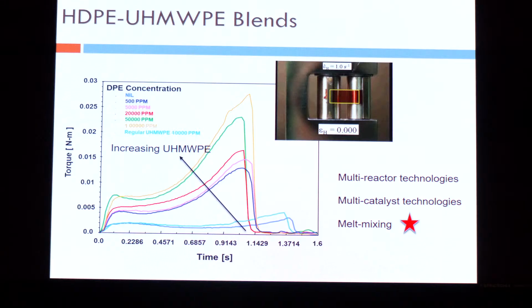90+% high density polyethylene. Now you can make these blends by many different technologies. I can have, for example, 2 different reactors, make high density polyethylene in one reactor, ultra high molecular weight polyethylene in another reactor, and mix them in the reactor itself. I can have 2 different catalysts. One makes high density polyethylene, the other makes ultra high molecular weight polyethylene in the same reactor, and I will get a blend coming out of the reactor.